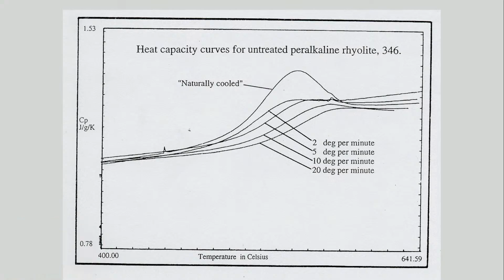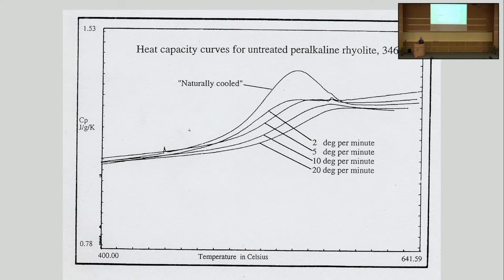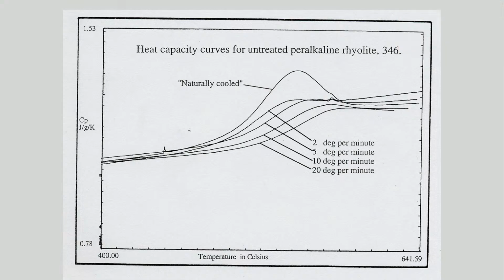And this is experimentally what the glass transition looks like. So this is the heat capacity versus temperature. So I'm simply heating something up from a low value on the left, which is the solid state, the glassy state. And then on the right-hand side, I have a high value of the heat capacity, which is the liquid state. And in the middle, I have something very interesting, which is depending on how quickly I heat it and cool it, I get a different value. So I have a hysteresis, I have a path dependence of the CP value depending upon the kinetics of the relaxation of the system. And we develop techniques to be able to do this on natural glasses. So we literally go into the field, take a fresh volcanic glass, bring it back into the laboratory, place it in the calorimeter, then we start to heat it and cool it at different rates and calibrate what this curve looks like depending upon what we did to it.